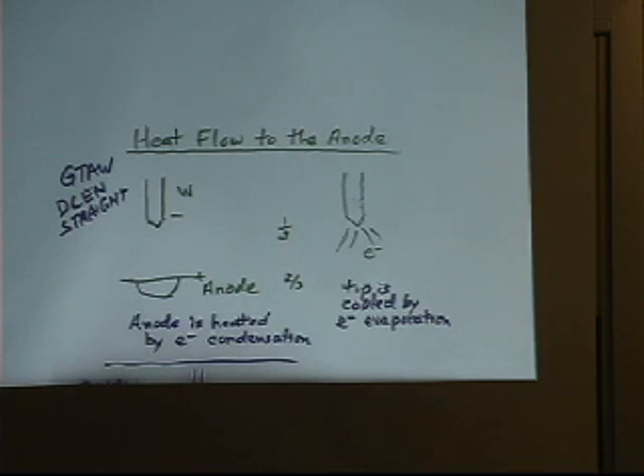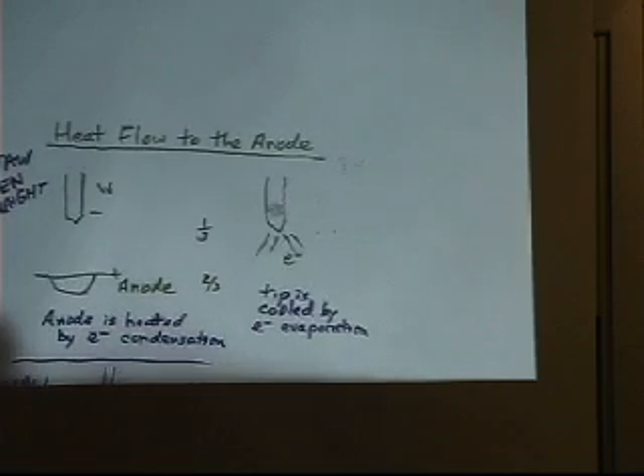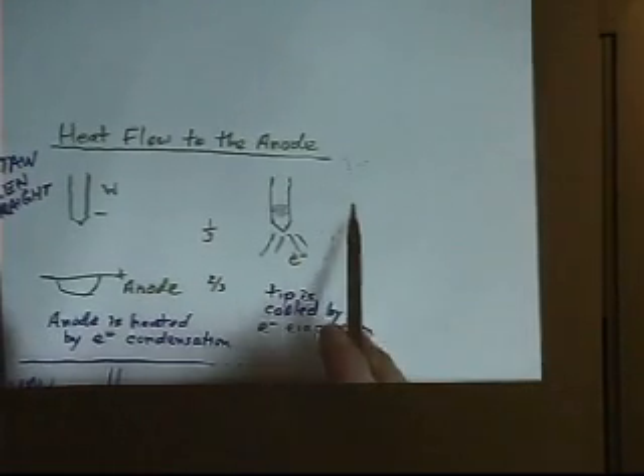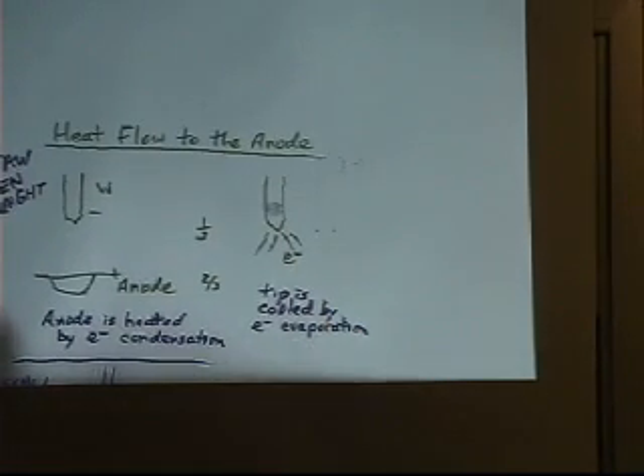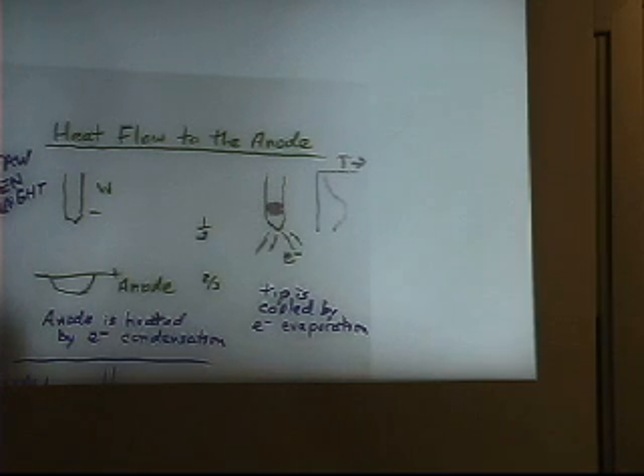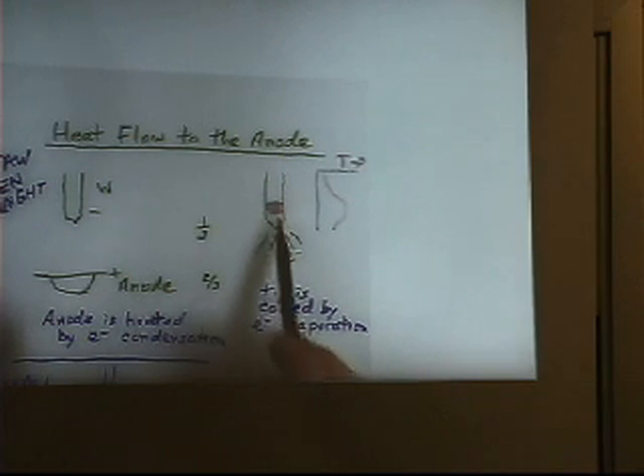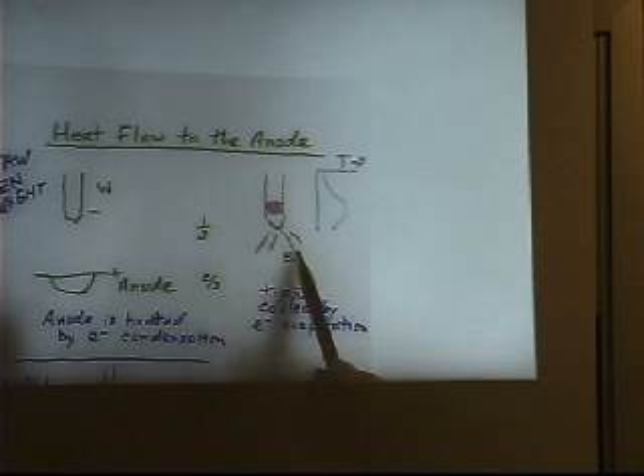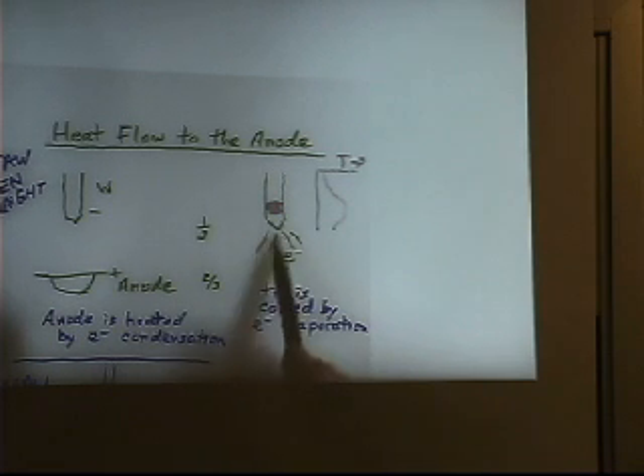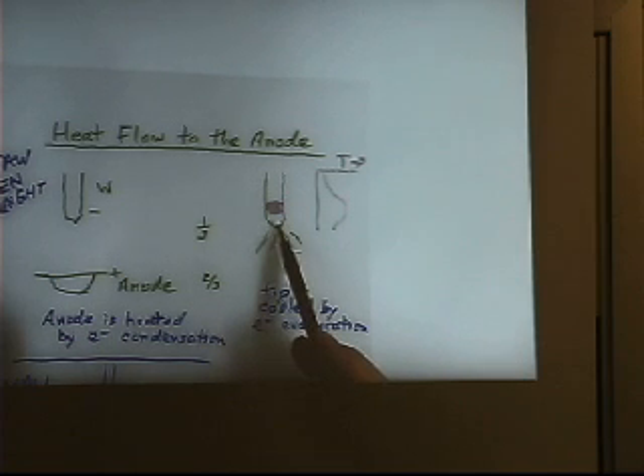And in fact, Professor Savage at RPI, who's passed away now, once put a pyrometer on here and actually measured the temperature and found you had a hot spot just up here, because basically the electrons evaporating out, you can think of them as evaporating out, are carrying the heat of evaporation with them and cooling the tip of the electrode.